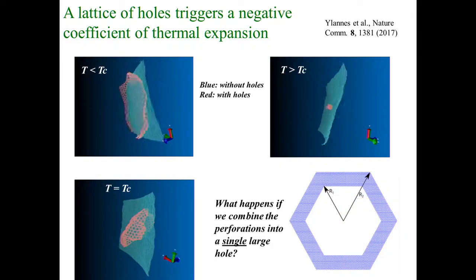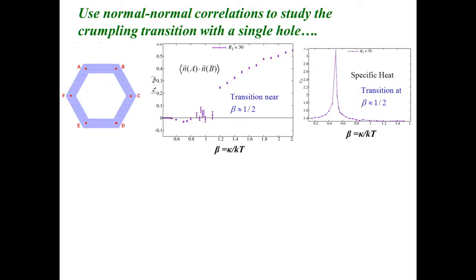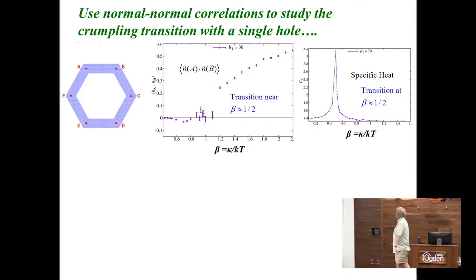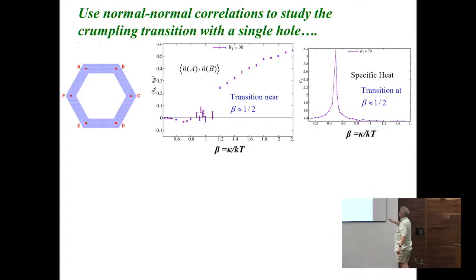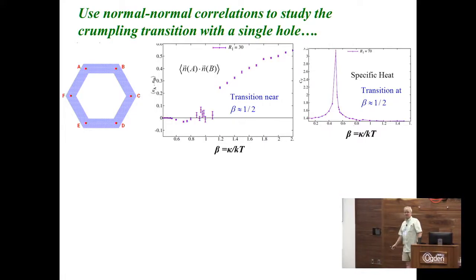There are lots of cool questions. And then, as has been alluded to by members of the audience, what happens if I take these holes and condense them into one giant hole in the middle, either a square hole or a hexagonal hole? I won't go through the details except to say that we've done some simulations and looked at the correlations of the normals, say the normal at A compared to the normal at D. And there is a kind of transition where these are correlated on opposite corners. You go to high enough temperatures, then they start flopping around and the normals no longer know what's going on. So if I go to high enough temperature, the normal correlation function goes to 0. That's accompanied by a singularity in the specific heat.